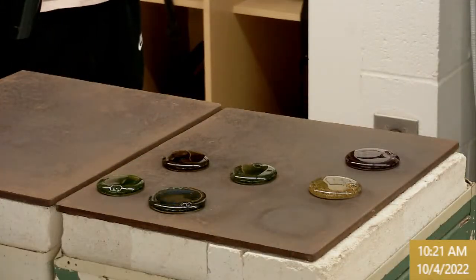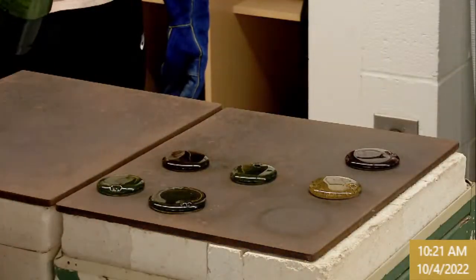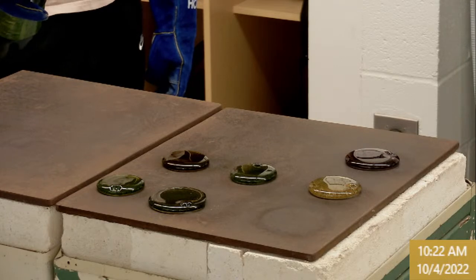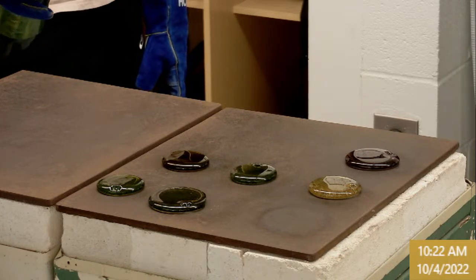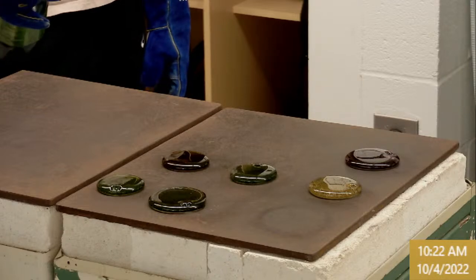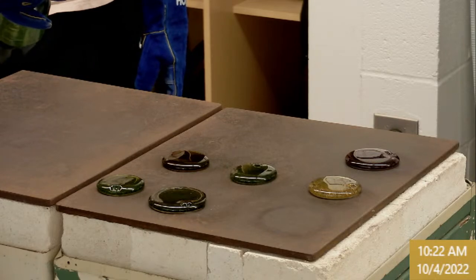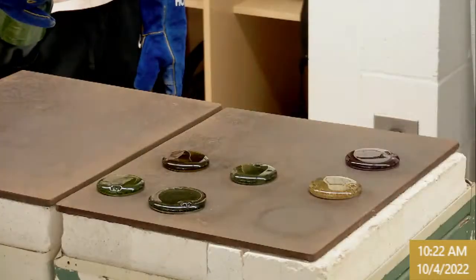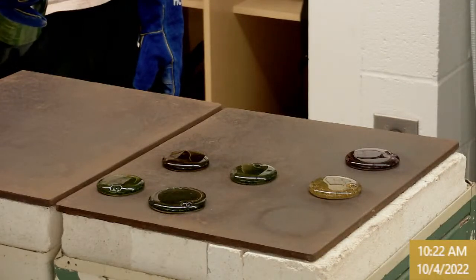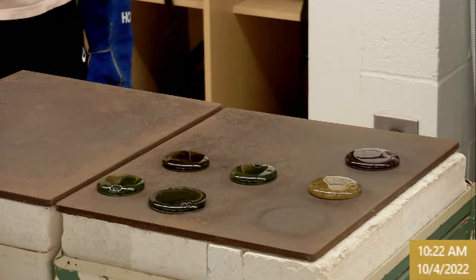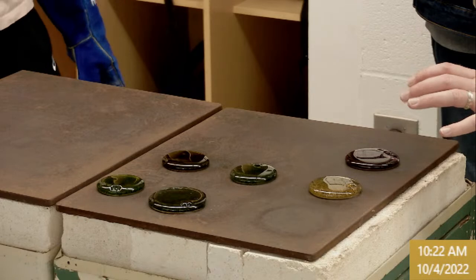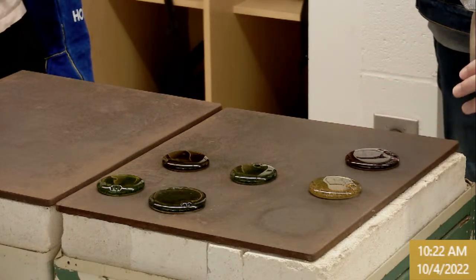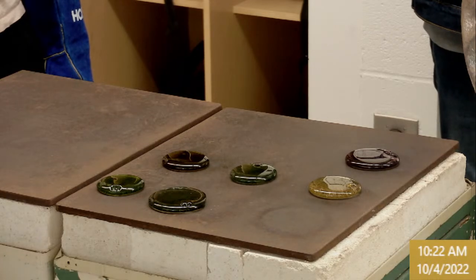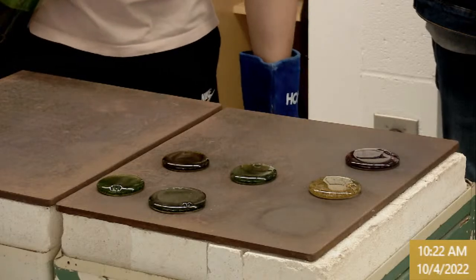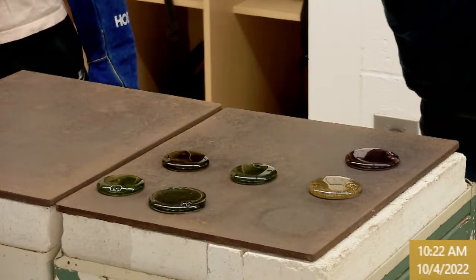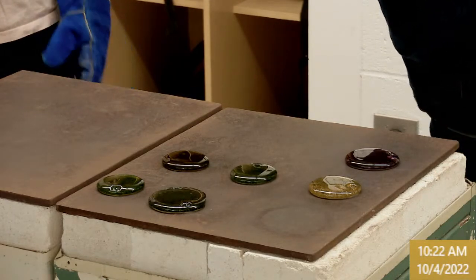So, okay, next up we have H2. And this one is 85 grams of mason sand, 50 grams sodium carbonate, 30 calcium carbonate, and this is 0.1 chrome. And this one used the clarifier, the 1 gram of sodium sulfate. And so for this one, we'll see if we see a big difference in bubbles. Like some of these, you'll definitely see more bubbles than others. This one is actually really clear. This one in particular has quite a few what appear to be little bubbles inside. So we'll see if it appears that the clarifier helped to remove bubbles. But mason sand plus chrome. So H2.